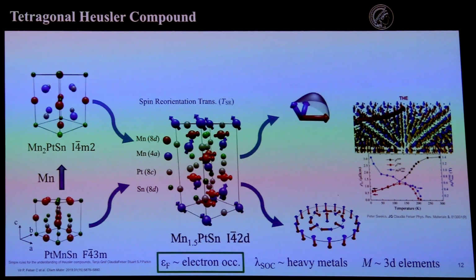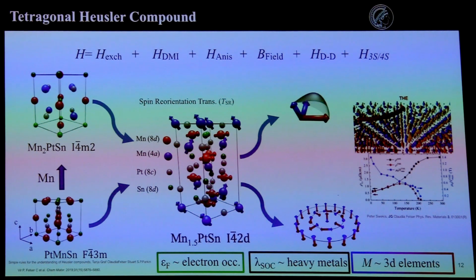How do you effectively change this? There's many ways to change this. You can shift the electron occupation, usually by the tin atom. If you change it to antimony or so, you put more or less electrons in, and that can change all of your parameters, such as your anisotropy, your exchange, your DMI. You technically can change the platinum, and you would think platinum has the largest spin-orbit coupling. And we'll see very soon that platinum is not the best case, but it really depends on what your electronic structure looks like. So you can really, by orders of magnitude, change your system by changing these atoms by 1 electron or so, or a very small amount in spin-orbit coupling. And then, of course, the magnetization comes from the manganese atoms.